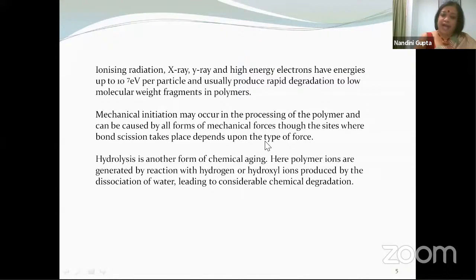Also, you might have mechanical initiation of chemical aging, because when you are processing the polymer, you cause it to be stressed by various kinds of mechanical stresses, and that can cause bond scission. Presence of water is another problem. I have already talked about water trees. If you have water present, hydrolysis of the polymer can take place, and the hydrogen or hydroxyl ions that are produced can cause considerable chemical degradation.